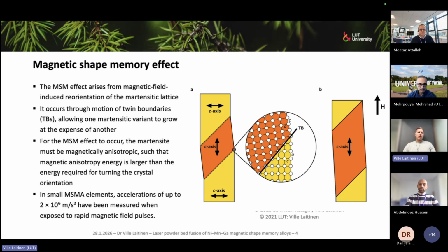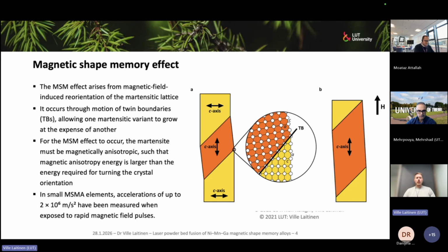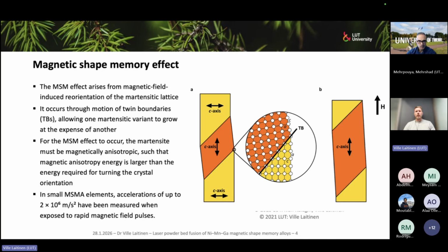And it's characteristic of this material that the magnetic anisotropy energy is significantly larger than the energy required for moving crystal boundaries, these twin boundaries between different martensite variants. So what happens when we bring in this external magnetic field is that the C-axis starts to exhibit magnetic field-induced stress, which tries to pivot the C-axis direction toward the direction of the external field. And this provides a pressure for these twin boundaries to be moved around. And since the variant which is in a preferred orientation grows at the cost of the variant which is not in preferred orientation, we will actually have a physical change in the material because of this flip of crystal orientation.